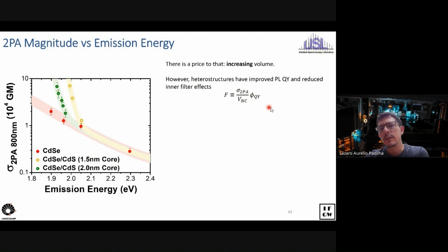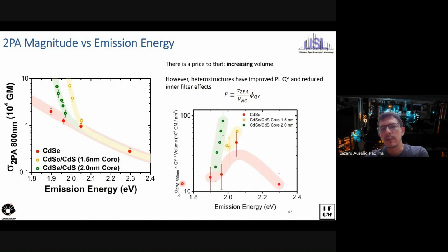But if you think, for example, in applications like two-photon bioimaging, for 3D bioimaging, you are interested in this ratio times the PL quantum yield. And if you do this and plot this figure of merit as a function of the emission energy, what we see here is that it's, again, better for the core shell structure than it is for the core only, simply because even though this ratio becomes slightly smaller, the quantum yield is much larger for the heterostructure.